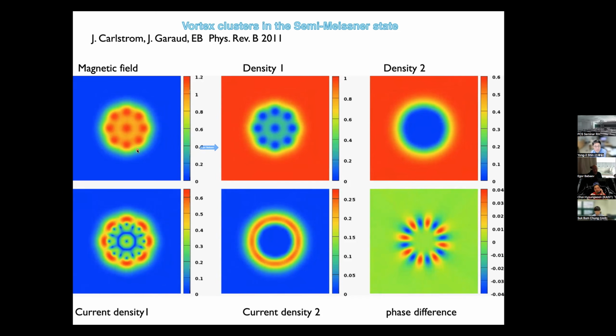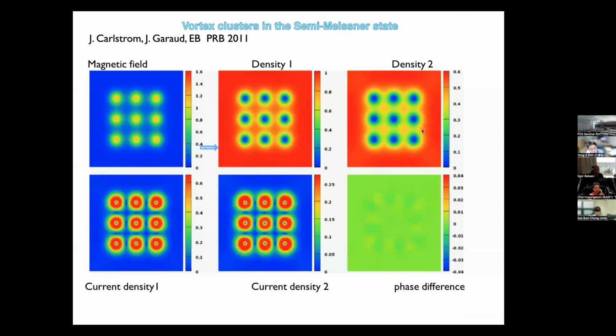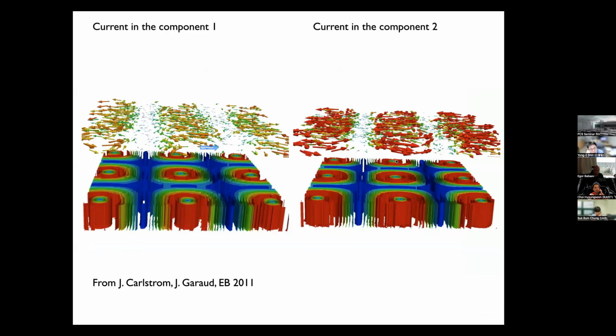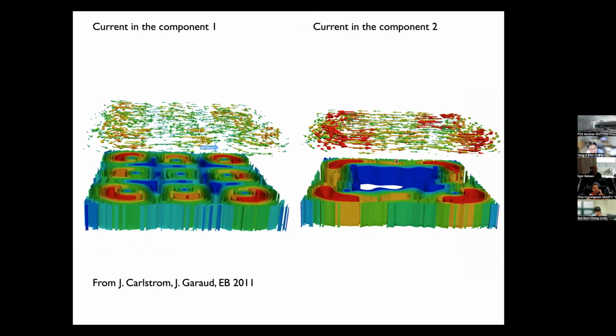Here nonlinear effects are important, and in this case you see that a vortex cluster forms where one component has vorticity, and the other component relegated almost all of its current to the surface of the cluster. One component has well-defined vortex cores, and there are also vortex cores in the second component, but you basically cannot see them. It's almost like one mega vortex. So basically this is what happens with currents in numerical simulations.